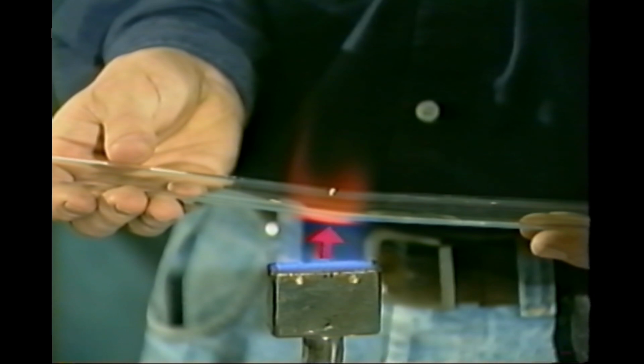The area of glass directly opposite the mark must now be heated longer. This area, when the tube is bent, will stretch and collapse, and the additional melting will allow this area, the outside radius of the bend, to be blown back to the correct diameter.